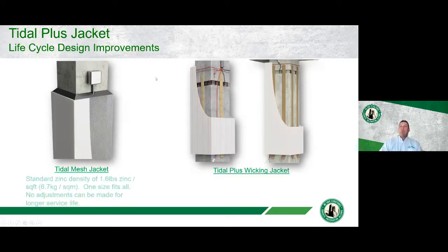So what do these improvements mean? We have our original mesh jacket, and we have the Tidal jacket now. What are these improvements? What do they do? When you install a Tidal jacket, you get a standard zinc density. We typically refer to it as 1.6 pounds of zinc per square foot of jacket, or 6.7 kilograms per square meter. It's one size fits all. Whether your pile is 18 inches in diameter or 40 inches in diameter, you have one density of zinc that you're going to use for your pile.